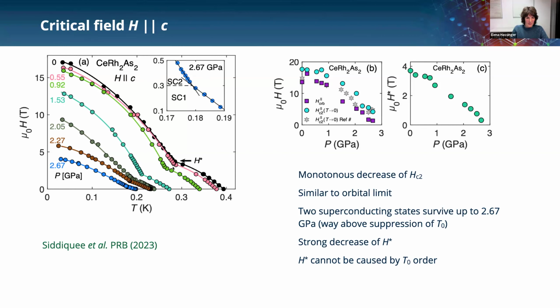Okay. What you see also in this data is this nice kink that occurs at H star, and the kink we can follow up to the highest pressure of 2.7 GPa. Here's a zoom, so you can clearly see the kink, and it strongly moves down in field. So this is what's shown here. It goes from 3.8 Tesla down to 0.3 Tesla.